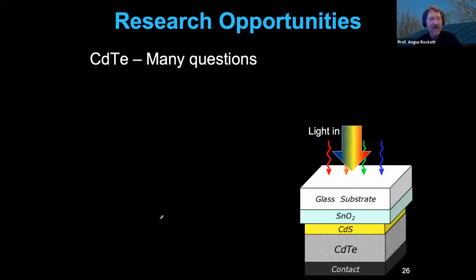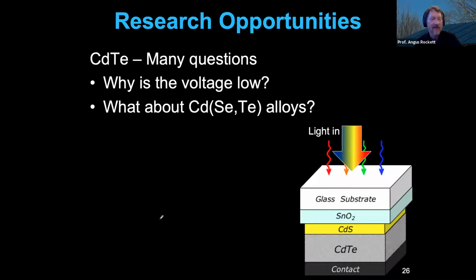Cadmium telluride has a lot of different questions. One of them is, why is the voltage so low? We should be able to get a lot more voltage out of a cadmium telluride solar cell. People are looking at alloys of cadmium selenide telluride, and that gives you the opportunity to adjust the band gap a little bit and potentially make a better performing device. We need to increase the p-type doping in the cadmium telluride because that's one of the problems that you have with this material, it's hard to dope.